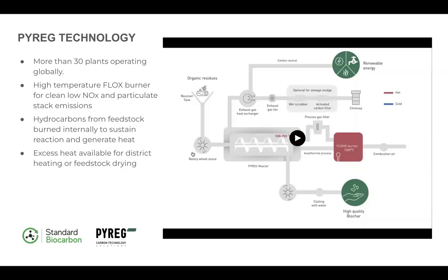The rotary wheel sluice is essentially an airlock where the wood is brought into the machine in the absence of oxygen. The wood then goes through the screw auger reactor right here at a temperature between 500 and 700 degrees centigrade, so very hot. And the gases from the wood get carried through this ceramic process gas filter and continue into the flox burner that I was just talking about, that burns at 1,000 degrees centigrade, so even hotter.